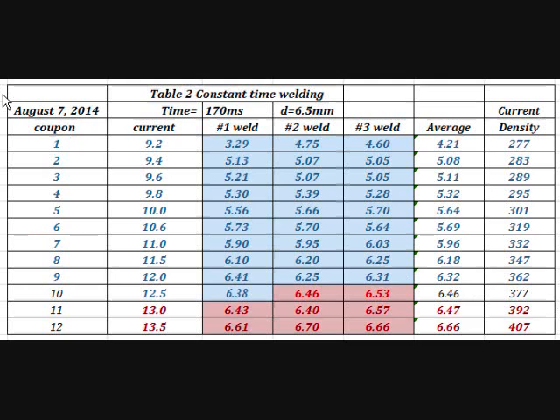This is an experiment run on August 7, 2014. The weld time is 170 milliseconds. The diameter of the weld cap is 6.5 millimeter measured. I started out with 9.2 kiloampere of current, and my weld average diameter is smaller than 5 millimeter. So I said, this is not good. Then I started 9.4 and started getting welds which are over 5 millimeter, which is good.